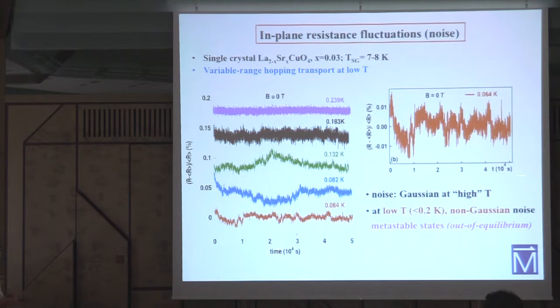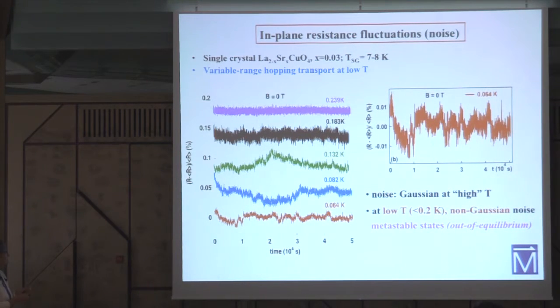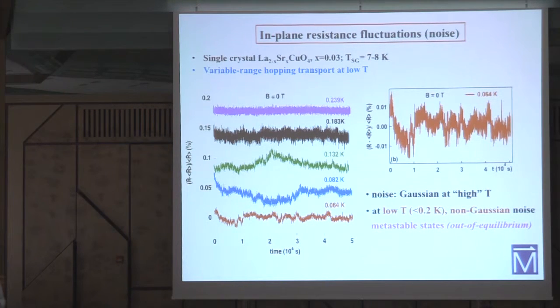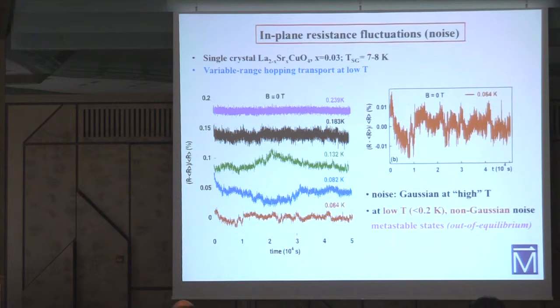There are fluctuations taking place over time scales of more than ten hours, as well as more rapid events. Non-Gaussianity of the noise means that the noise looks different depending on the measurement time window — in other words, in a given experimental time window, different states contribute to the measured resistivity. The system does not have enough time to explore the entire phase space, meaning it is non-ergodic, or glassy.